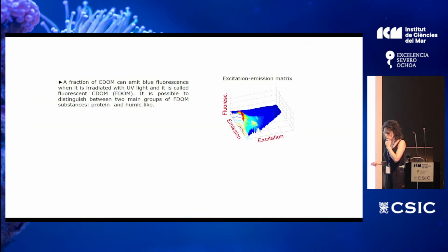Another thing that we do to know more about the dissolved organic matter released by plastic is to measure its fluorescence, because, as I said before, it's very difficult to study the chemical composition of the natural dissolved organic matter, but we have a proxy to study that composition, and it's through its fluorescent properties. So we know that a fraction of the natural DOM has the capacity to absorb UV and visible radiation, and that fraction of the DOM is called colored dissolved organic matter. And a fraction of it is able to fluoresce, to emit the absorbed radiation in the form of fluorescence. And this property of fluorescence is what we use to know more about the chemical composition of the DOM.